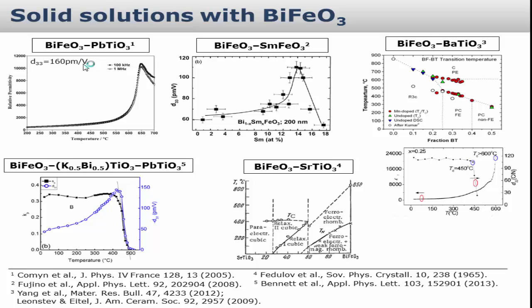Now, when you go to a complex system, when you start to modify bismuth ferrite heavily, for example by making a solid solution, these are some examples from the literature. We heard something about such a system today by Tim. There are some others. Things get much more problematic because now you have several components, several oxides with very different diffusion coefficients, and things become complicated. I will show an example on this system with which we work right now, this family of bismuth ferrite and alkaline earth titanates. And I think it shows, in principle, what is the major problem of perhaps all or many of these kinds of materials.